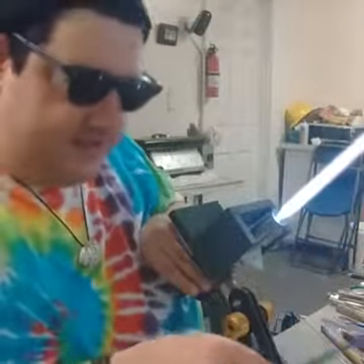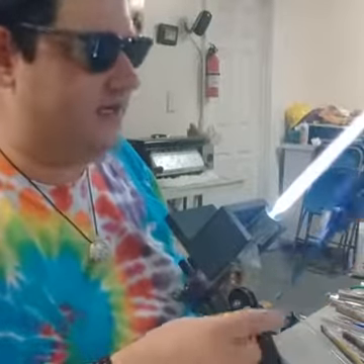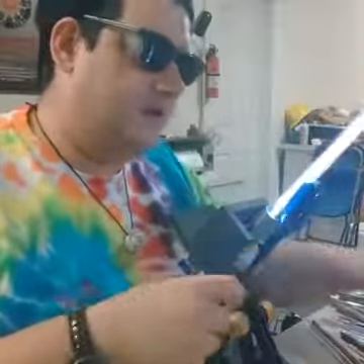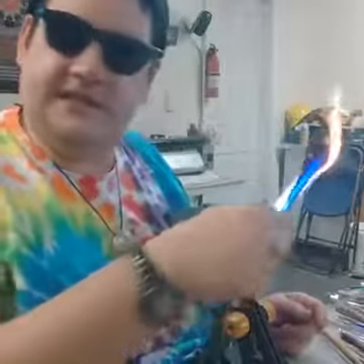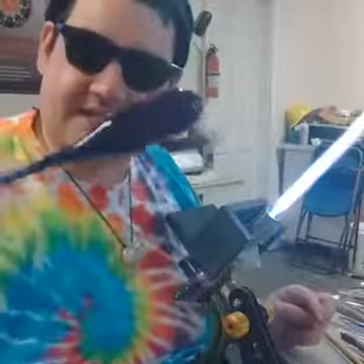So I just went back in my kiln and I got a fresh blank. This one I'm going to do with silver fume. So I showed you guys a minute ago that piece of silver I have on that clear rod. And what I'm doing right now is I'm adjusting my flame chemistry to what's called a reducing flame. A reducing flame has more propane in it than it does oxygen. And that's the type of flame that you need to be able to vaporize the fine silver that's on the end of this rod and ultimately have it stick to this glass.